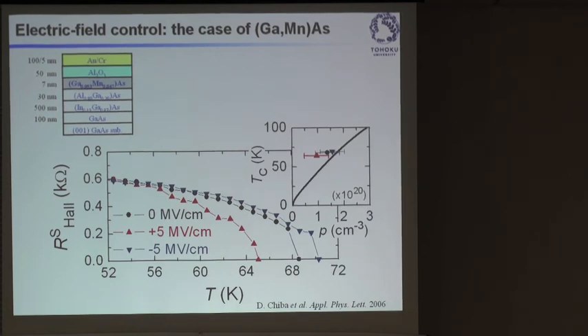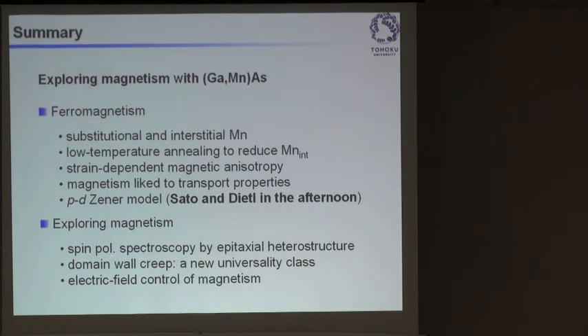So basically, what we have done is that we synthesized a new material. We made gallium arsenide ferromagnetic, and we tried to understand the ferromagnetism we see in this material. First of all, we wanted to see where manganese is in the lattice, and we also noticed that there are a considerable number of interstitial manganese as well, which we can remove by low temperature annealing after growth. I didn't discuss strain-dependent magnetic anisotropy, for the interest of time. And magnetism is clearly linked to transport properties because we can measure magnetization by the Hall effect. And we also have developed a p-d Zener model that describes many aspects of the experiments we see in the system.